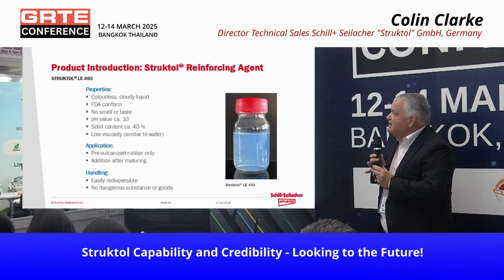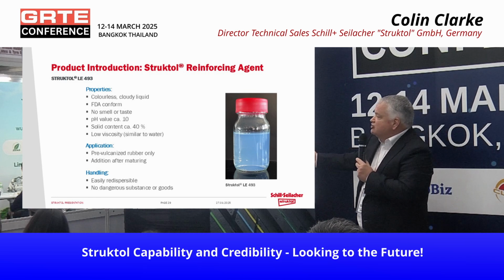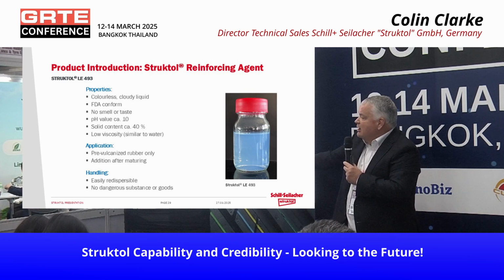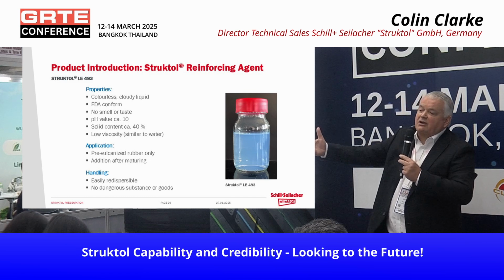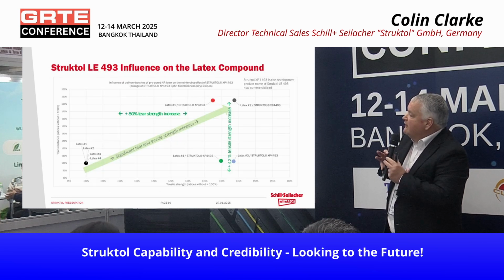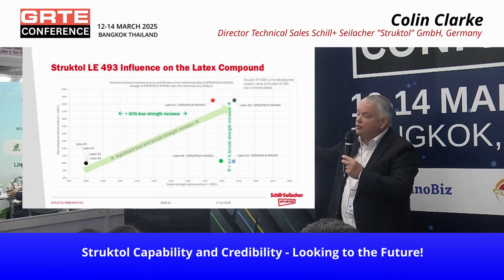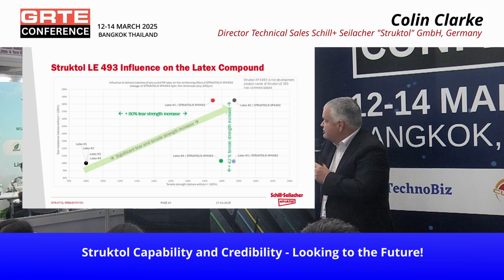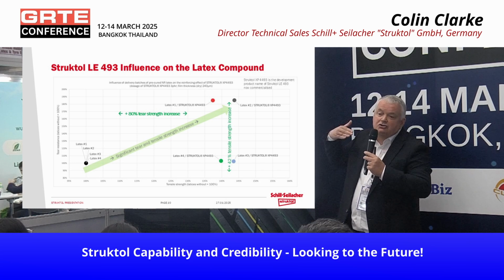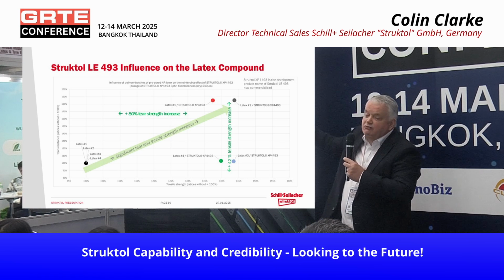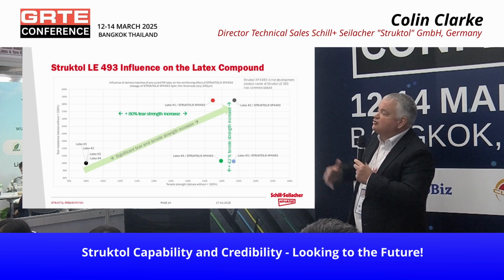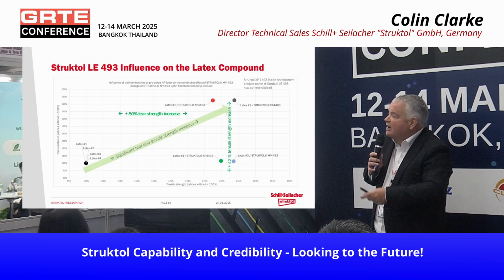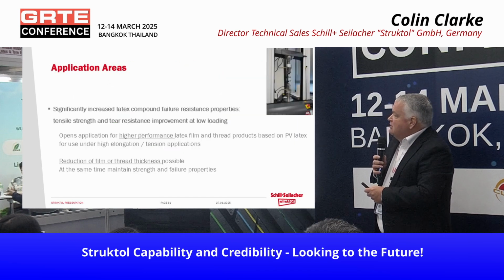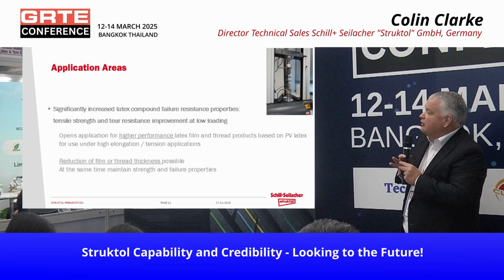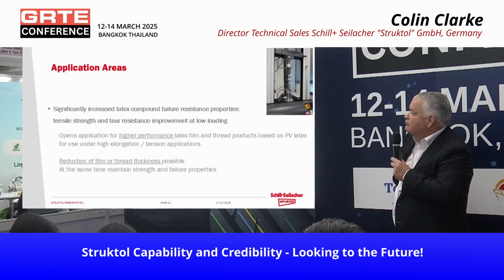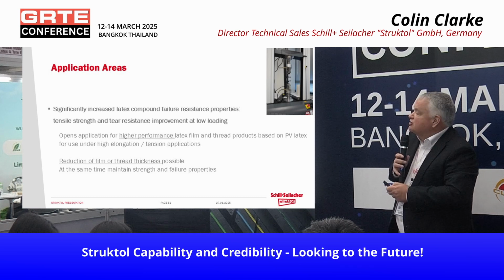One new product that we produced, if you like, for latex is a reinforcement agent. This is a water-based dispersion with a high solid content, 40%, but it's a real nano material. With very low loading, we can improve significantly the latex strength properties. So for example, if we look at the tear and tensile strength with the 3 PHR loading of our reinforcement material, we can increase tear by 80%, really raise up 140% in terms of the tensile strength. So applied into natural rubber, especially pre-vulcanized natural rubber, significant improvements in latex tensile and tear with a very low loading of a reinforcement additive, with very high stability, so we don't see any separation or stability issues. So we can reduce the film thickness for the same tensile and tear properties, so really improving, if you like, the mechanical properties of latex compounds.